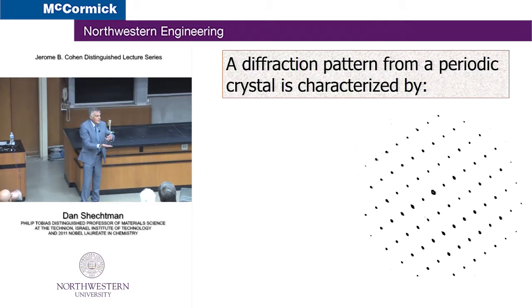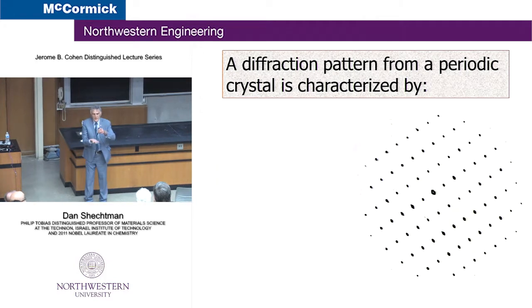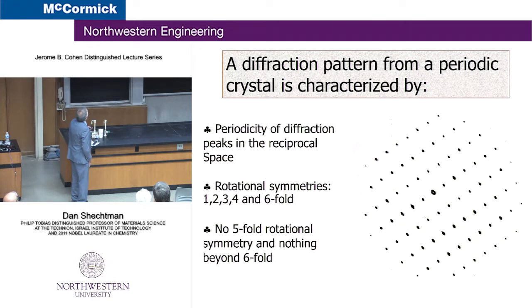It's very thin because you made it very thin. And part of the beam goes through, and this is the central beam. This is the transmitted beam. And other parts are elastically scattered to form a diffraction pattern. And these are the rest of the spots, okay? And there is some more to it, but we are not going to dwell on that too much. So this is a diffraction pattern from a periodic lattice. And you see that there is periodicity here. The rotation symmetry of this crystal is also 1, 2, 3, 4, and 6, much like in the real space. And 5-fold rotation symmetry is not allowed.